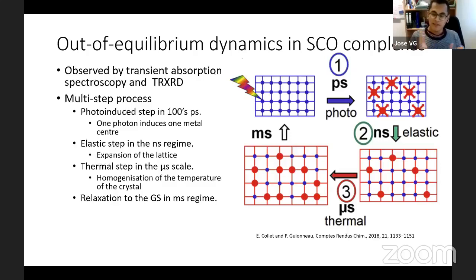And usually the elastic and the thermal steps are higher than, or surpass, the pure photo-induced process. So we usually have more transition from low spin to high spin because of the heating or because of the elastic deformation of the material. And finally, we can say the last step is the recovery from the thermal step to the original ground state we started from.